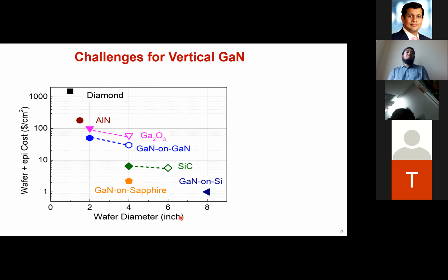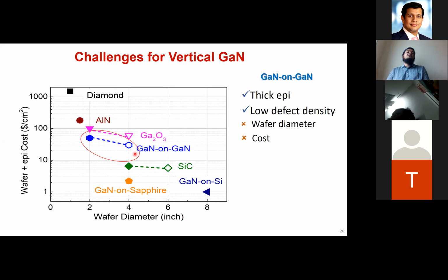So a primary challenge for this gallium nitride technology is the wafer. In silicon technology today, they use 12-inch diameter wafers for mass fabrication. Having a larger diameter helps to maximize the yield and minimize the cost. But if we compare what kind of substrate we can have for gallium nitride, the devices I showed in the previous slides are fabricated on pure gallium nitride substrate, or so-called GaN on GaN. The wafer diameter for this device is 2 to 4 inches today, and the wafer cost is close to $100 per centimeter square. But since it's gallium nitride on gallium nitride, the quality is very high, and we can grow thick gallium nitride layers to support larger blocking voltage.